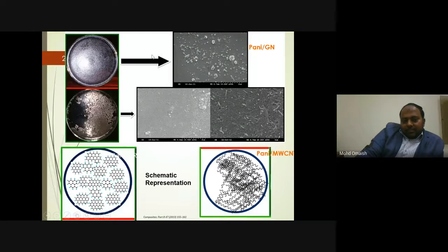This is one of our old papers, maybe a decade back, where we synthesized a polyaniline graphene film and a polyaniline carbon nanotube film. Here we found that the dispersion in the case of polyaniline graphene is much more uniform in comparison to polyaniline carbon nanotubes, which we later improved.